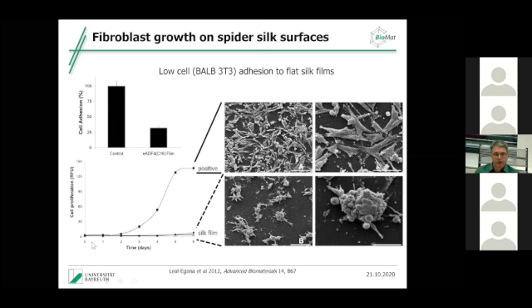If you make a proliferation test, so if you look over days at what happens with the cells, you see that they agglomerate, they still are in a spherical shape, they're not attaching to the surface, they're not spreading out, and they're not proliferating on the silk surface. But they do, of course, on the tissue culture plate. This was a very first indication that in the native state, the spider silk is probably pretty much like a cell-repelling surface. But that's not bad, because sometimes you want to have that inside the human body, so that the body cells cannot recognize the surface. So we thought this could be a clever idea to protect implants.